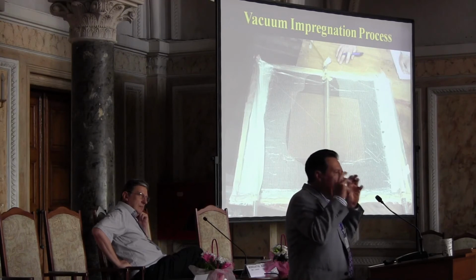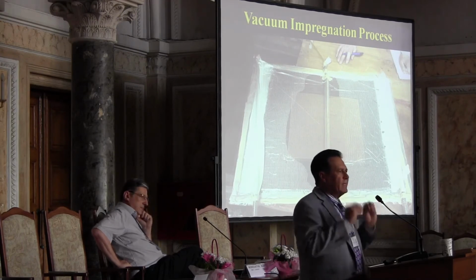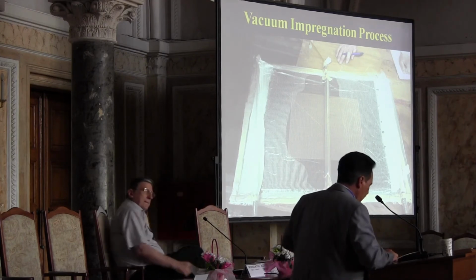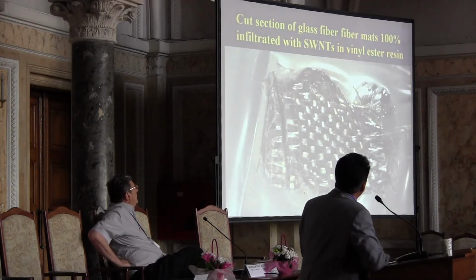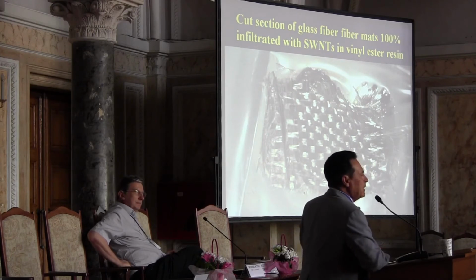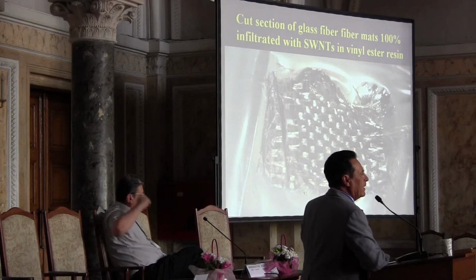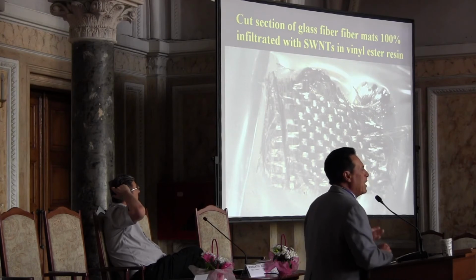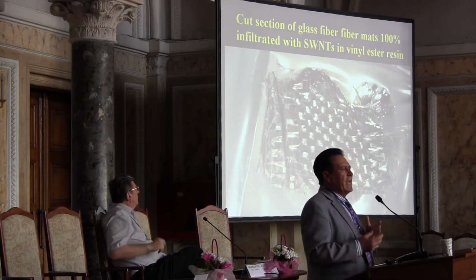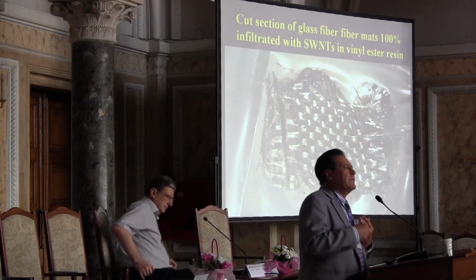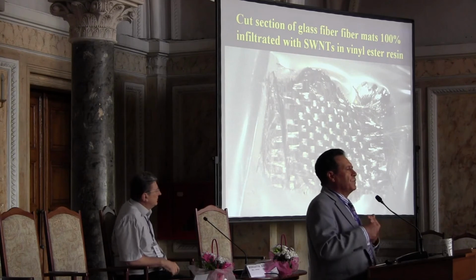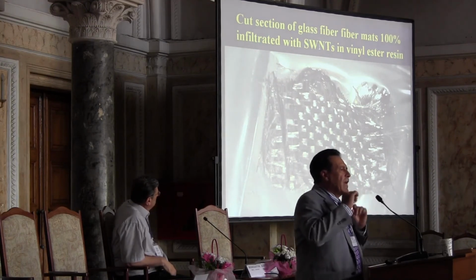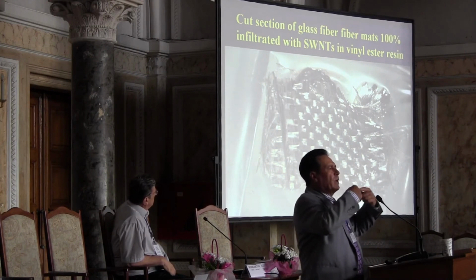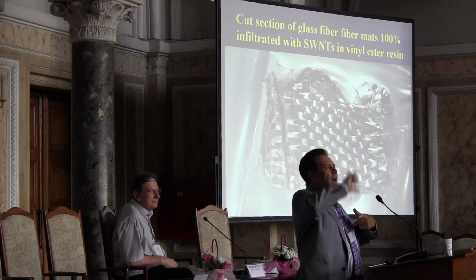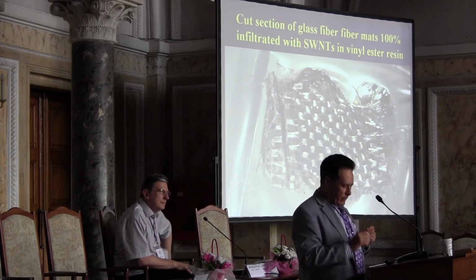incorporate these matrix reinforcements only in critical places, where we need them. And as you can see, this is a 3D glass fiber primary reinforcement that has been fully infiltrated by these carbon nanotubes. So what you obtain is higher resistance to fatigue crack initiation and higher resistance to fatigue crack propagation, because you have the carbon nanotubes now perpendicular. So if you have the glass fibers in one direction, you have the carbon nanotubes perpendicular to this direction.